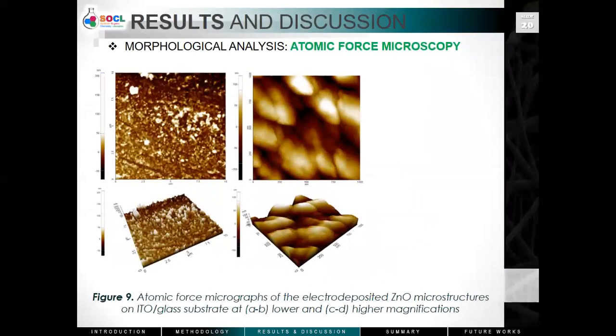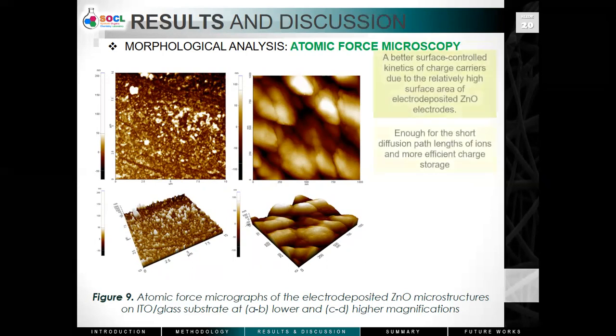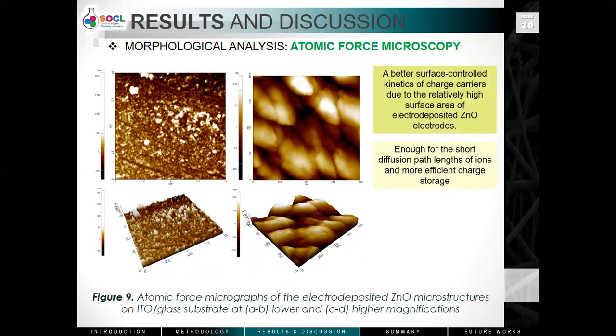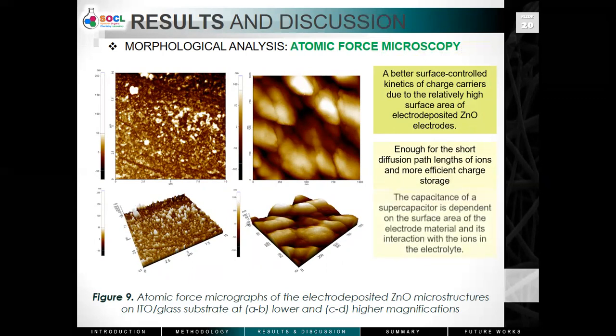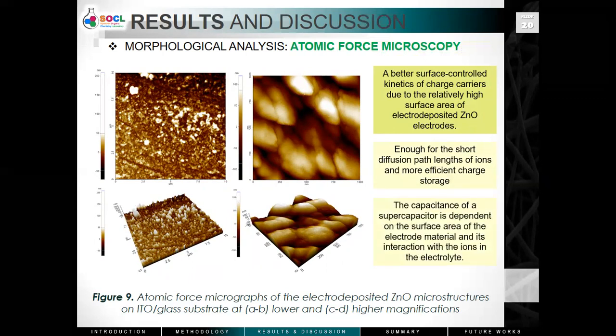In addition, as shown in the atomic force micrographs, the use of deposited zinc oxide microstructures as electrode material may have afforded a better surface-controlled kinetics of charge carriers due to its relatively high surface area. It is noteworthy that the capacitance of a supercapacitor is dependent on the surface area of the electrode material and its interaction with the ions in the electrolyte.